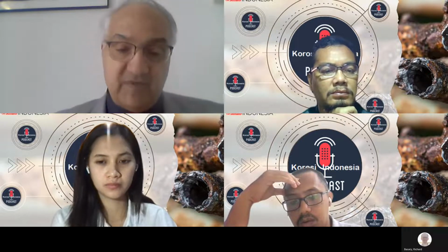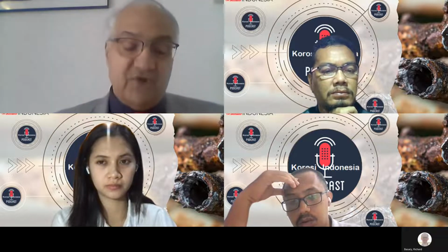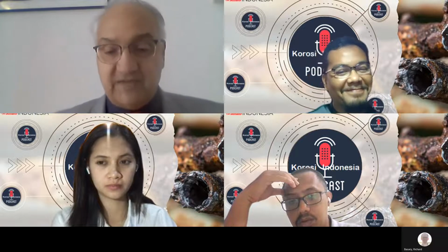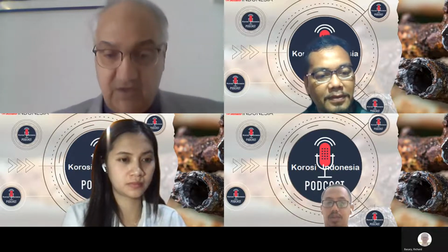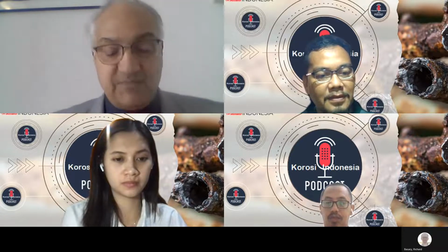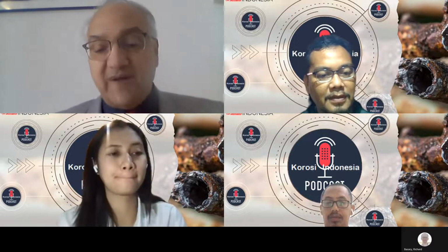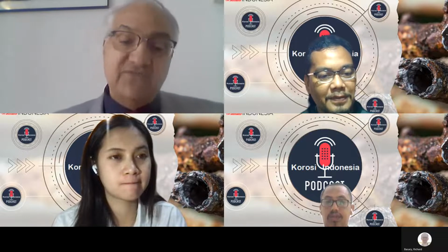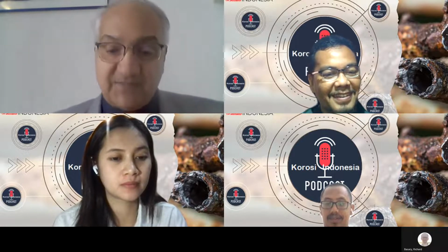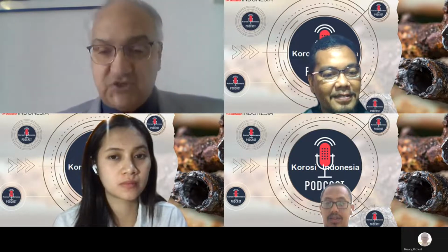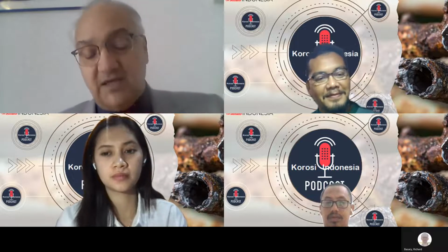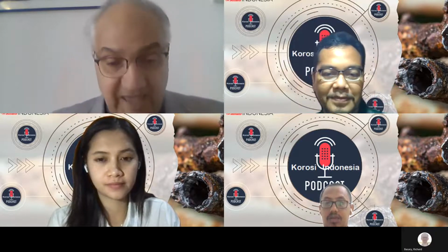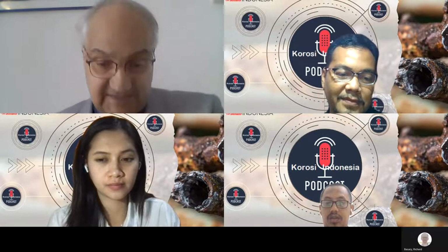For those of us who may remember their undergraduate courses, Pourbaix diagrams, you would remember that these Pourbaix diagrams are constructed based on pH and corrosion potential. Okay, in industry, when an engineer sees that the pH, for example, is 7, he automatically assumes that the conditions are not corrosive. However, if you go back to the Pourbaix diagram, you see that even at pH 7, if corrosion potential is around a certain level, the environment could be corrosive. If pH is 2, however, and the corrosion potential is around a certain level, your system could be not corrosive at all. So just by looking at pH, you cannot tell a story about your system.